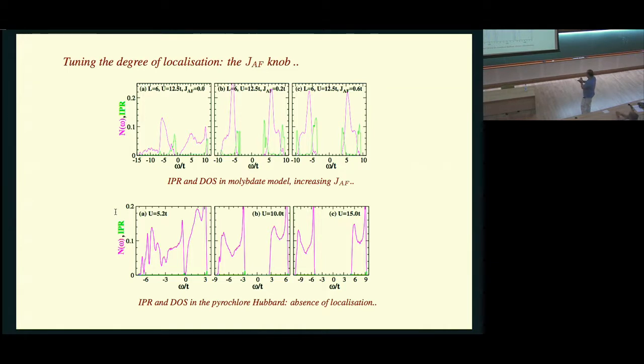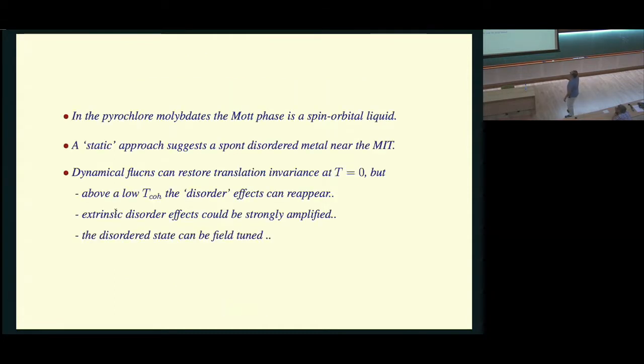So, come to the conclusions. Conclusions. So, obvious statement, the Mott phase is a spin orbital liquid in the molybdates. The static approach, now this is the big caveat, suggests a spontaneously disordered metal, and the absolutely vital question is, if you did turn on dynamical fluctuations of the fields, the magnetic and the charge field, would it restore translation invariance at t equal to 0? Hard calculation. We can do perturbative sort of Gaussian fluctuations on top of this, but I don't know whether there is a clean answer that comes out.